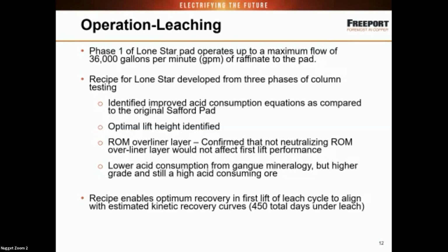We identified our optimal lift height, which is typically 16 to 20 feet. We started our first lift at 16 feet, but we included the 4-foot ROM overliner and made the decision, based on column testing, to leach it all at once. And we didn't pre-neutralize our high acid consuming or potentially acid consuming ROM layer. It was very successful. We'll talk about that a little bit later.